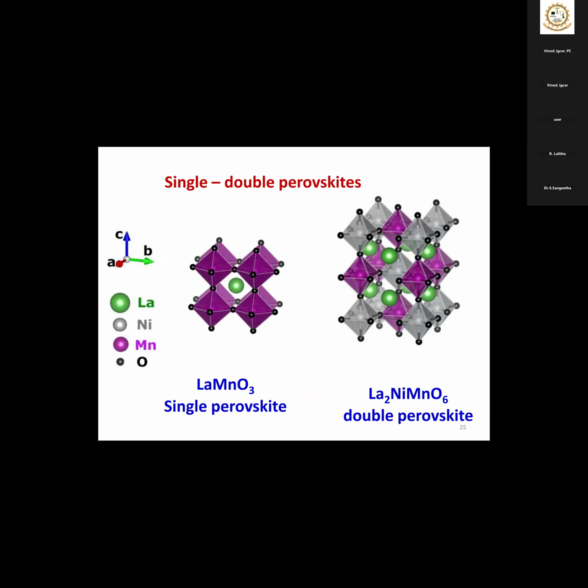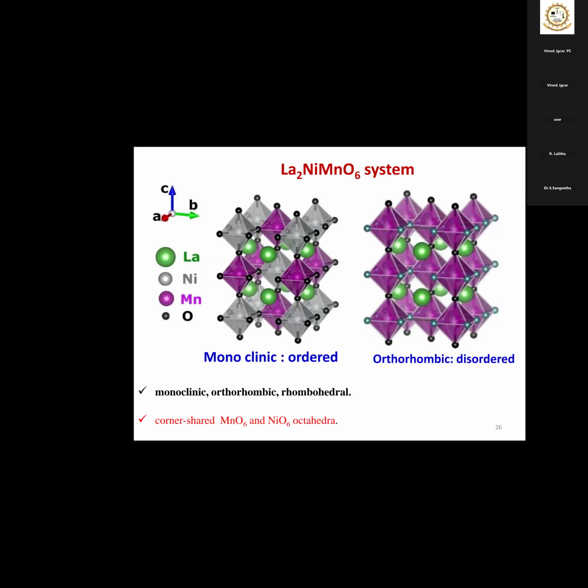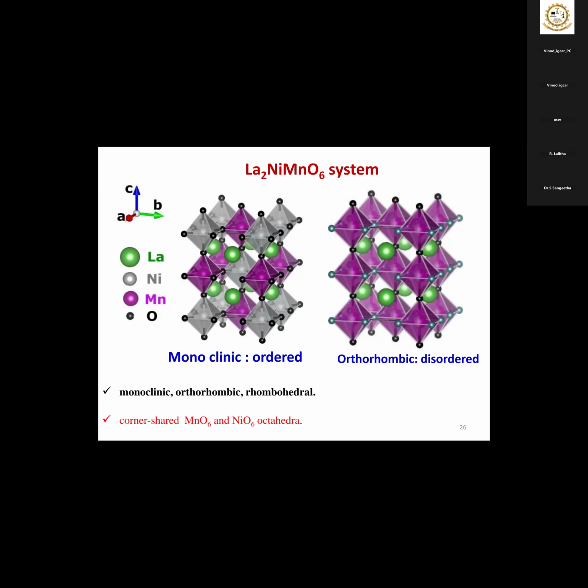Earlier it was a small primitive cell. You see, left is one single perovskite primitive cell, LaMnO3. Now one manganese site you removed and replaced with a nickel site, and it is perfectly ordered, which means due to symmetry the primitive unit cell volume is doubled. That is why it is labeled as double perovskite. And now the stoichiometry is La2NiMnO6. This is perfectly ordered. I will show you there is another way to get La2NiMnO6. Here you see La2NiMnO6, it is perfectly ordered.